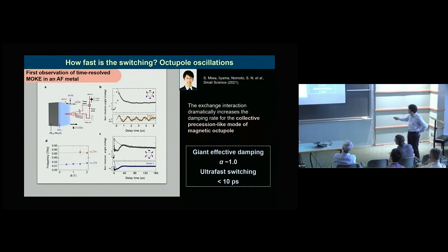So the Kerr effect actually shows the precession as a function of the delay time, indicating this spin, or octopolar moment, does precess at the time scale of picoseconds. But it decays very rapidly, indicating there is a giant effective damping. And this is actually useful for switching for us to develop a memory, because once we let the spins precess, it actually stops automatically. There is a strong damping due to, I would say, strong correlation of this material.